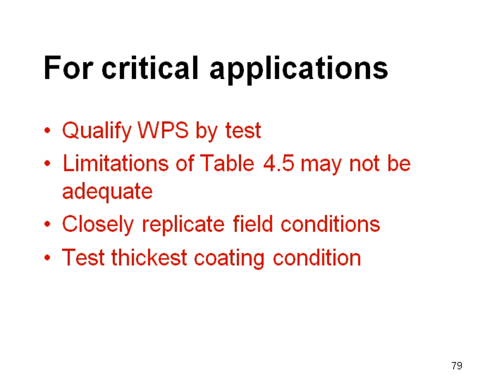However, bullet point 2, my words, Table 4.5 may not be adequate. That's really hard for the chairman of the D1.1 committee to say. I'm not speaking on behalf of the committee, but in my opinion, they're not adequate for some of these applications with coated materials. We need to be a little bit more restrictive. I say that because I've had experience where test welds were fine and too great a deviation from the test conditions was employed and resulted in problems on the actual project. So I recommend that you closely replicate the field conditions. Whatever you're doing in the field, mock it up, test it, see if you have any quality problems. I also suggest that you test the thickest coating condition that you're likely to encounter.